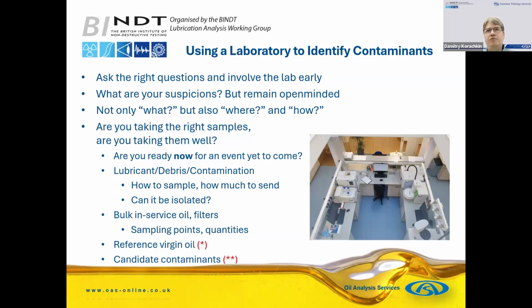So for reference, if there's AdBlue contamination in fuel, if it's significant, there's normally a layer of separated fluid at the bottom of the jar, which you can then test and find out if it's water, something else, or if it's AdBlue. There was no separation there. The sample was black. When we performed the routine analysis, we found trace engine oil additives and a layer of black sediment, likely soot contamination. So it looks like there is sooty engine oil getting into the fuel, and that's something that the customer can investigate, but it was not in line with the initial assumption of AdBlue.